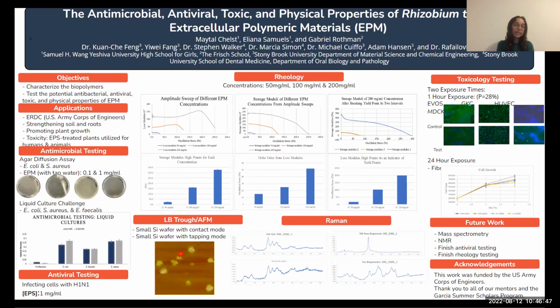For our repeated test, we utilized a liquid culture containing E. coli, S. aureus, and E. faecalis, incubated overnight. And we observed our results through calculating the optical densities of the various liquid cultures with and without EPM. And we found that the difference between the presence and absence of EPM was not statistically significant.